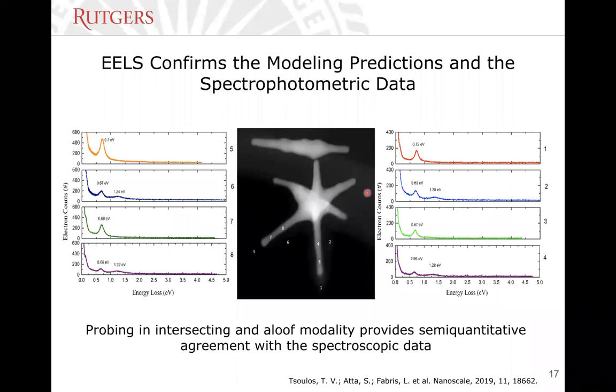For instance, what we did, we took this nanostar and we probed two spikes in two different modalities. We probed the aloof mode, where the electron beam is shown far from the spike. And we probed the intersecting modality, where the electron beam really crosses the spikes. And so what we saw is that in the aloof modalities, which is positions 5 and 6, we clearly can probe the first harmonic mode, and in one case, the second harmonic mode. And this is also the case for the intersect approach. However, we see some slight deviation in the resonant peaks.